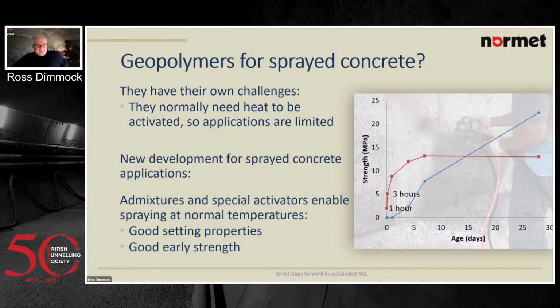This is super safe for the tunnelers, but it sort of stops after 6 or 7 days and goes flat and stays at 15 MPa roughly. But I think there are ways that we can push up that strength, up to 20, 30 MPa. And according to my designer friends, that's no problem as long as they know what they've got. They can design linings on it. But it's interesting, we could really drop the cement down to 0 if that's what we need to do.